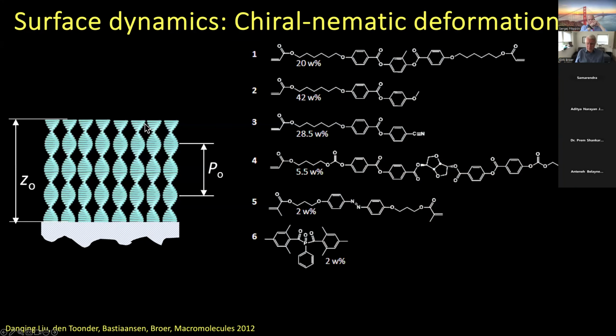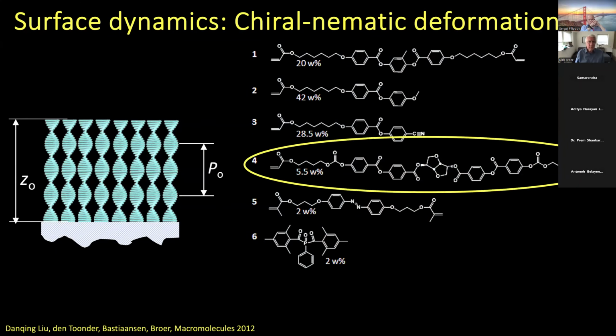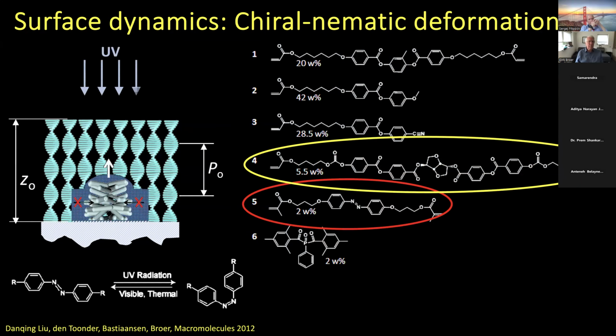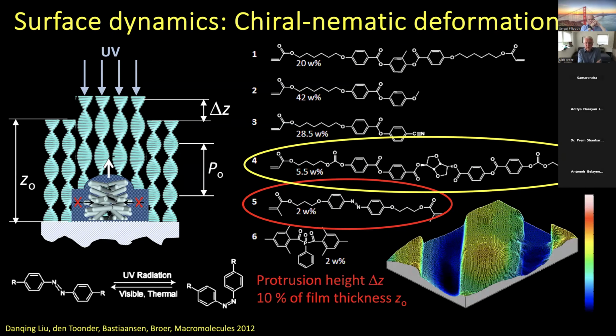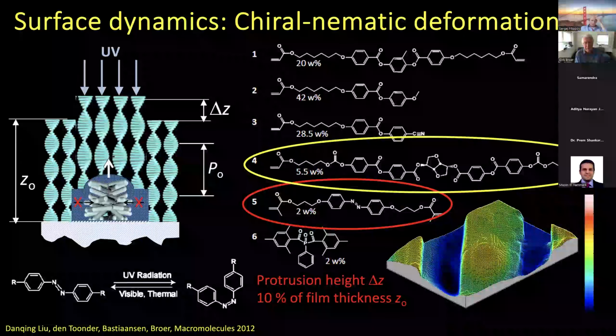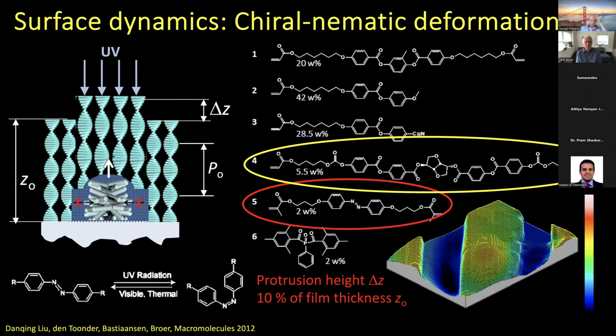And now, after polymerization, we start actuating the azobenzene locally by light, and then, just as with the thermal actuation, you change the degree of order in the helix, and for that reason, at the position where you expose the film, it starts to expand. The expansion is rather high, actually. It is about 10% of the film thickness. So a 10 micrometer film gives 1 micrometer thick protrusions, which was a little bit higher than we could explain just based on the other parameters.